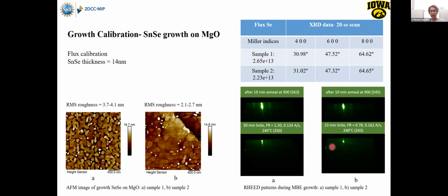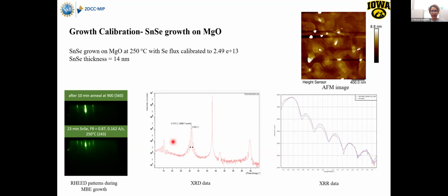Then we play with the flux ratio. I don't think I need to explain about this. You can see how film quality improved by changing the flux ratio. Also, as I said, this is recipe development, so it's not just that we play with the flux ratio. I think at this result, we also changed the substrate temperature. And then at the end, we could get the tin selenide with a thickness of 14 nanometers.